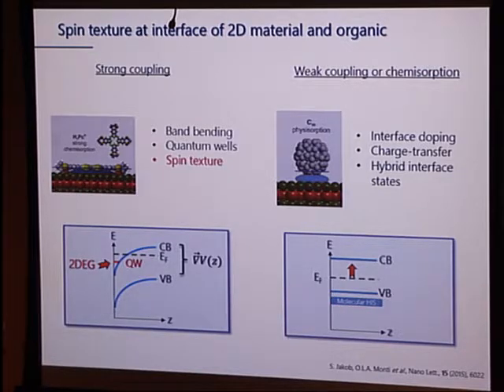And so when we compare and contrast to the weak coupling, then in that case, all we did is we modified the overall electronic structure a little bit. But the spin texture arises in a new fashion, in a totally different way, purely from the electronic interaction between the molecule and the surface. So this is something you can do by using molecules, and you can create qualitatively new behavior.